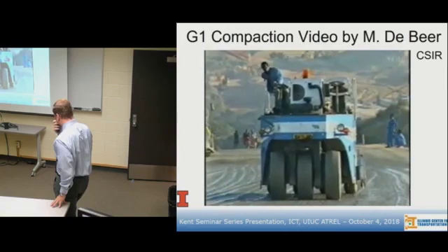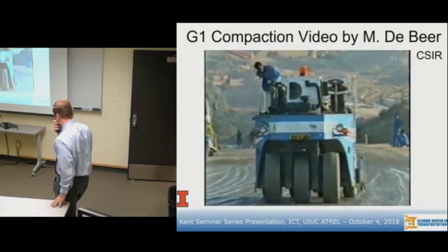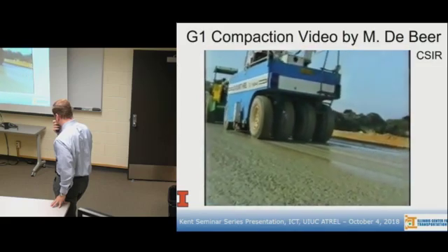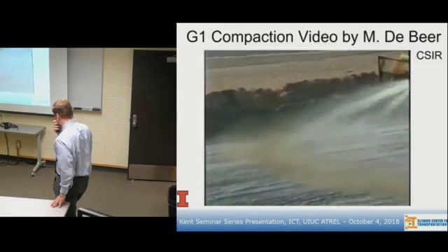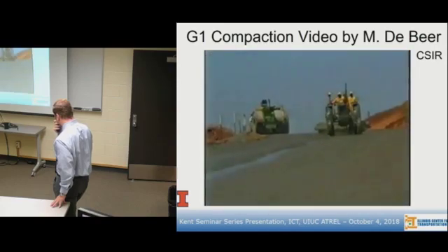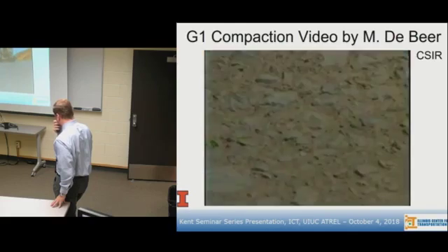When the pneumatic tired roller leaves no indentation on the surface, it is a good indication that the layer has been slushed sufficiently. The process is ended by thoroughly wetting the surface again and brooming off the free water and any remaining slush without disturbing the interlocked surface texture. The layer should now have a uniform and firmly interlocked mosaic appearance and be allowed to dry off.